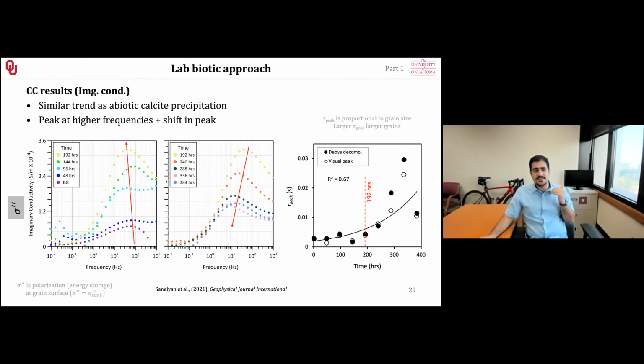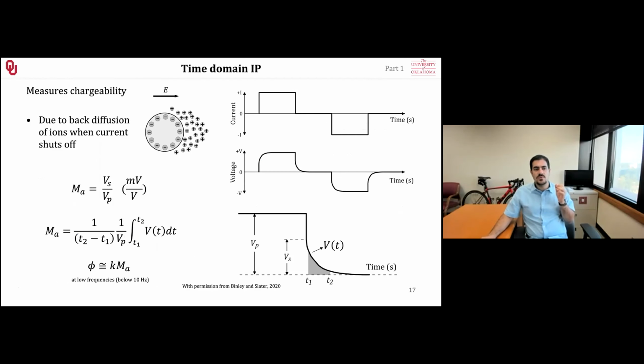We were also able to see that the peak is not only changing in magnitude, but also decreasing in frequency. This is very interesting because it allows us to calculate basically the size of the grains that we have. If you remember from here, for instance, when the ions want to distribute around this grain, they need time. Now, if that grain is big, it takes them more time. If that grain is small, it takes them less time.